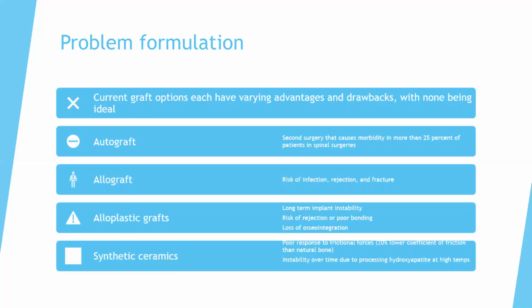There are also inherent limitations of alloplastic grafts, such as long-term implant instability, rejection by the host body and infection, injury to the nervous system, and loss of osseointegration. For ceramic grafts, limitations include poor response to lateral forces, poor response to frictional forces, potential voids created by manufacturing defects leading to lower compressive strength, and instability over time due to the high temperatures that hydroxyapatite is processed at.